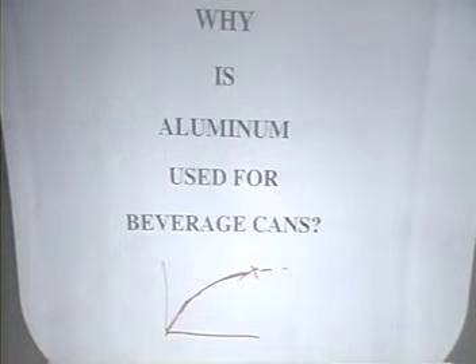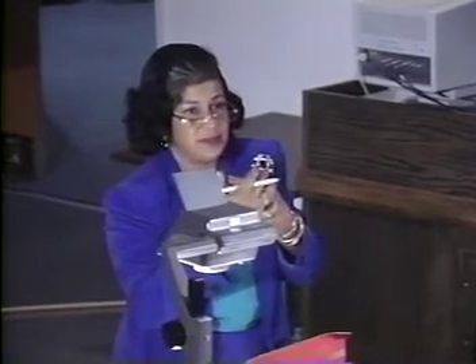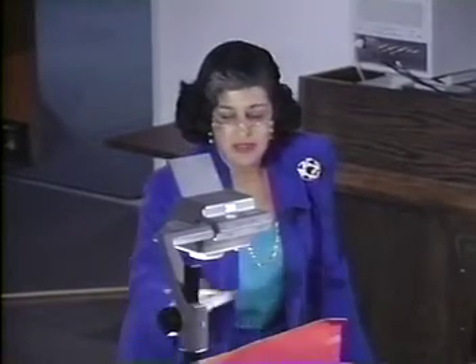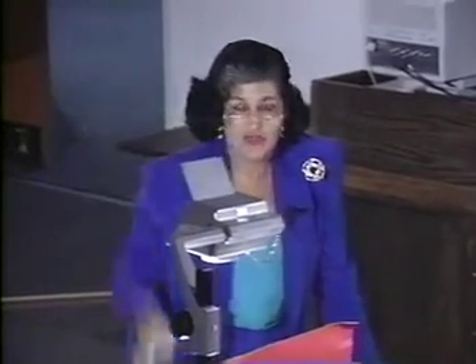So what you typically do is keep it warm so that with increased warmth, atom mobility increases with temperature. So some of your defects, the atoms will rearrange themselves to eliminate some of the defects. Okay? And so if you do it in the warm range, this rearrangement is occurring while the deformation is occurring. So you're minimizing the effects of the defects. Most of this is warm to cold working. The rolling is done when it first starts off hot and cools with successive rolls.